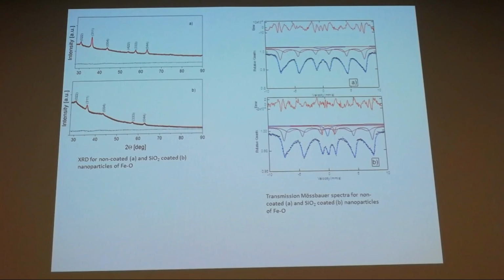Mössbauer spectral analysis showed the presence, for the coated nanoparticles, of an additional component of the convolution, which was a singlet line, not seen for the non-coated sample, which has to be actually confirmed. There are two possible explanations for that. One is that the nanoparticles are separated by this coating, and this results in a transition to a sort of superparamagnetic state. But I'm not convinced about that. I would rather assume that the iron atoms on the surface of the nanoparticle interact with the surroundings, the silicon oxide surroundings, and thus this affects the shape of the Mössbauer spectrum.